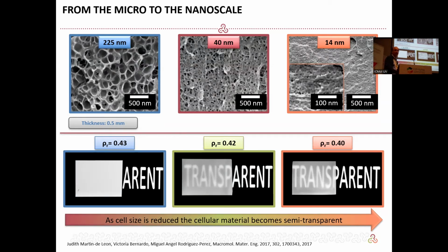So we have created, in this slide, transparent materials that at the same time are very good at thermal insulation, and they have very good mechanical properties. So this is a kind of combination of properties that is not easy to reach, because we have transparent materials, silica, PMMA, but they are not thermal insulators, okay? Or we have silica aerogel. This is transparent, but the mechanical properties are very poor.